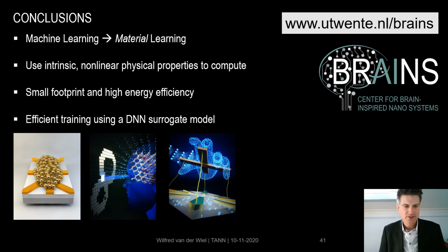That's a big advantage. The other advantage is that you are not so prone to defects. You don't need to have a perfect device layout, but you can start with disordered systems and then use material learning to realize the functionality. That's at the same time also the downside. For every individual device, you have to go through this learning phase, because no device is the same. What we have shown is that we can realize functionality at a very small footprint and with a projected high energy efficiency. And the last thing that I have showed you was efficient training using a surrogate model consisting of a deep neural network. This is an alternative, as an intermediate step, an alternative for this artificial evolution.